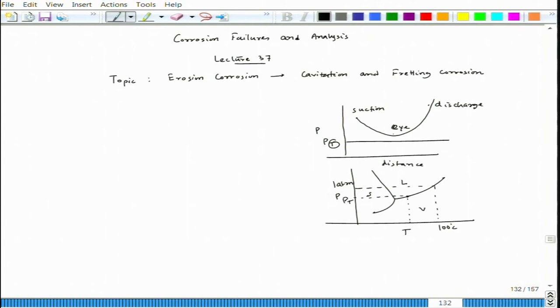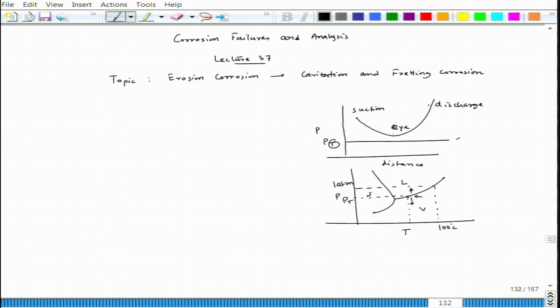If the pressure reaches p_t and then goes below it, liquid and vapour coexist at equilibrium. If pressure drops further, steam forms; if pressure rises, liquid forms. So between suction, intermediate, and discharge points, if the pressure drops below the vapour pressure p_t, boiling happens, steam bubbles form, and when pressure recovers those bubbles collapse.